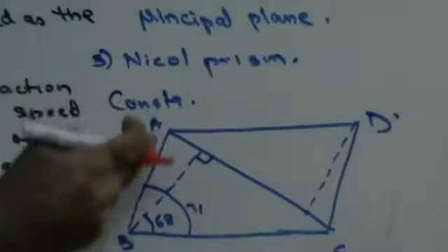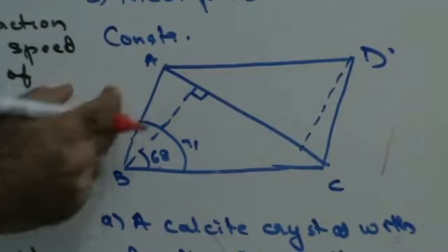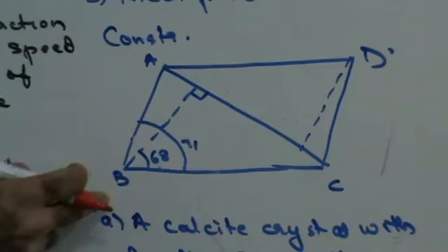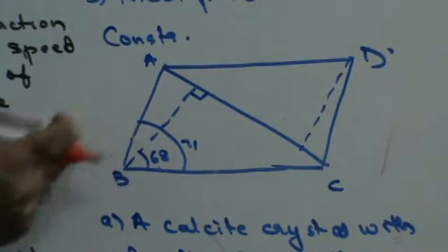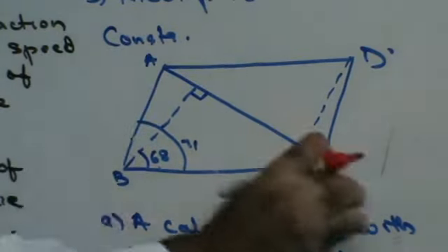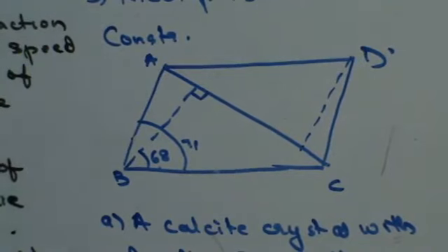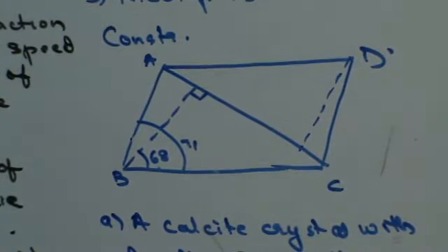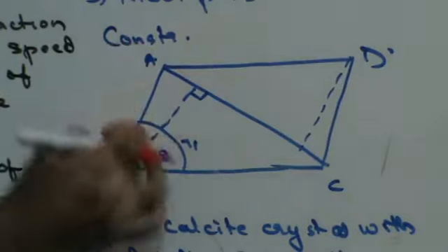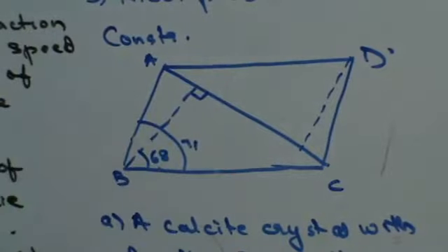So you take a calcite crystal whose length is 3 times its width. You file the two short faces till the angle reduces from 71 degrees to 68 degrees. Cut the crystal along the principal axis, polish the two surfaces, put a thin layer of glue, which is your Canada Balsam, and stick it together. And the two long sides, you're going to blacken with lamp black. That's it. Fine, do we get this thing clear?